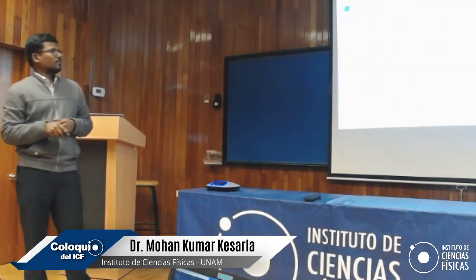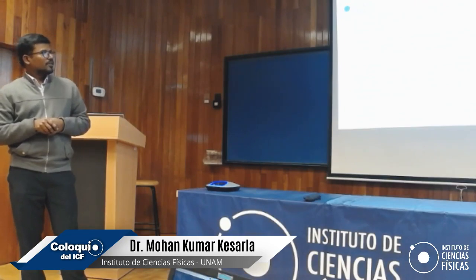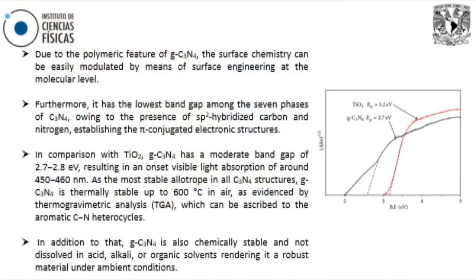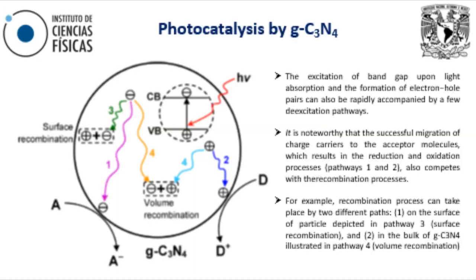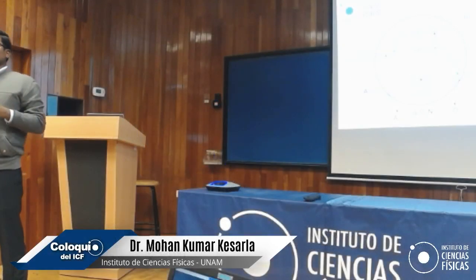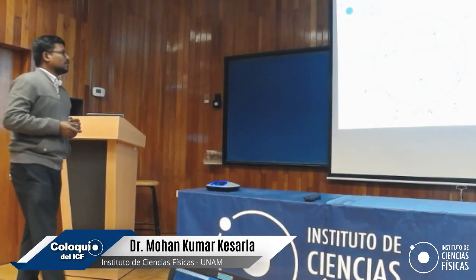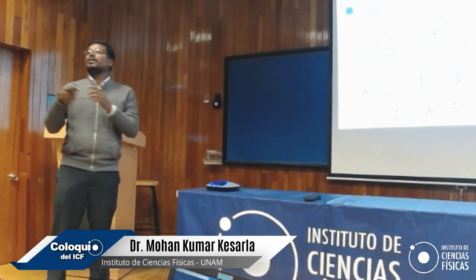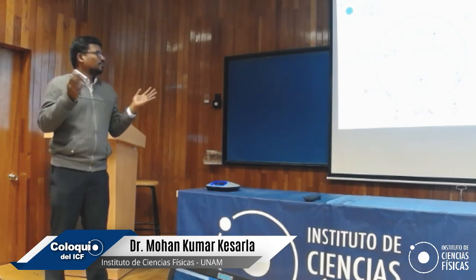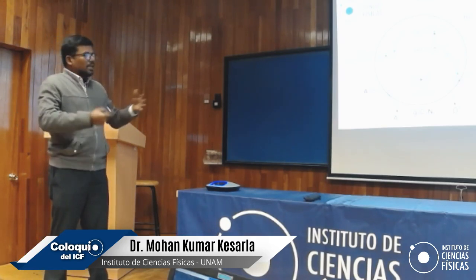And it has a good band gap compared to TiO2. TiO2 has 3.2 electron volts, and g-C3N4 has 2.7 electron volts, which makes it a good visible light photocatalyst. Now, how will the photocatalysis of g-C3N4 help in producing hydrogen? If you excite this g-C3N4 with an energy higher than or equal to the band gap of the material, electron-hole pair formation will take place. But at the same time, there is one more thing: the electron-hole pairs recombine back.